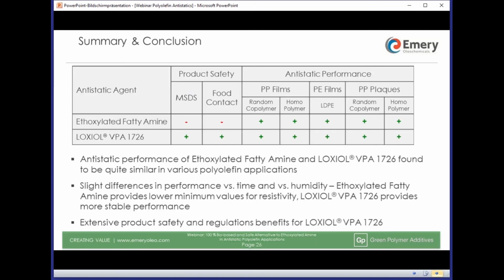The table here again provides a helicopter view, a very high flying helicopter view, as all the details have been provided in the last 20-25 minutes. We know that ethoxylated fatty amine and LOXIOL VPA 1726 have not shown an identical, but an overall quite similar performance, with some benefits here and there for the one or the other product. Ethoxylated fatty amine might provide some lower minimum values for surface resistivity, but performance, on the other hand, is more influenced by storage time or film age and humidity. But overall, both products are well-suited antistatic agents.